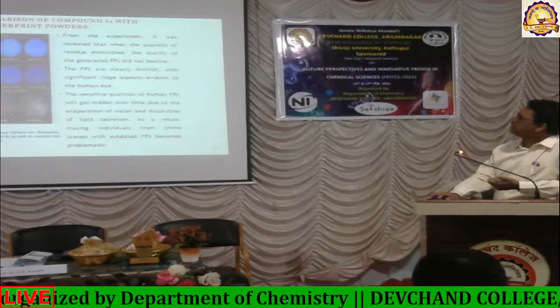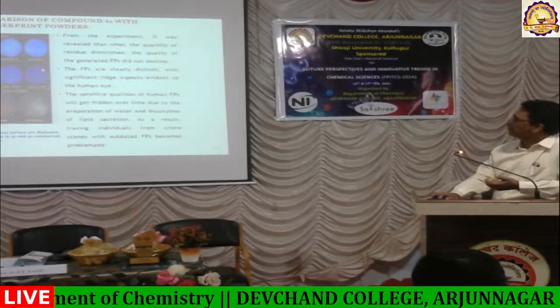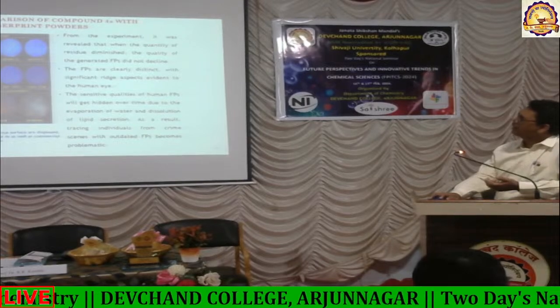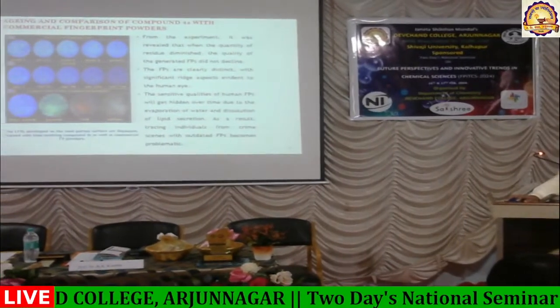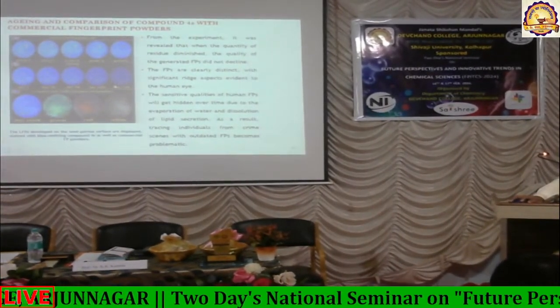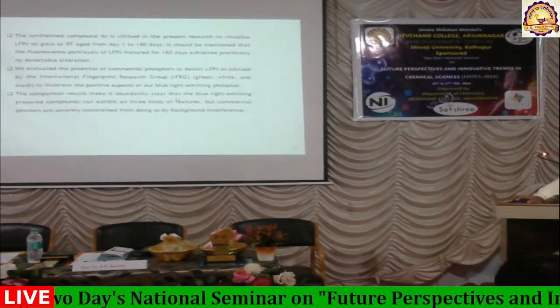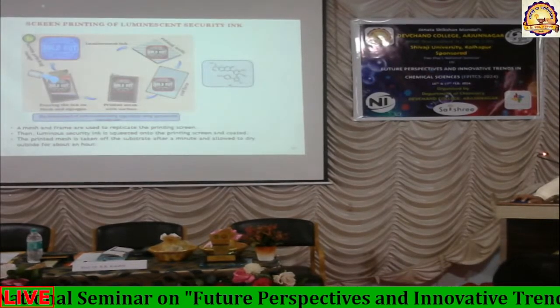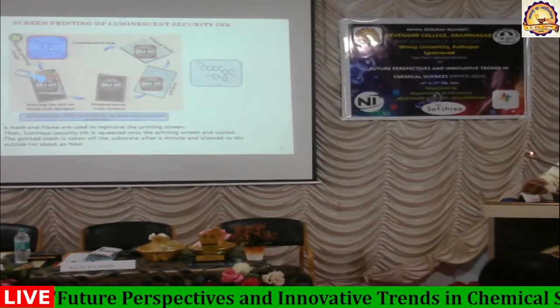So this is about aging. This is about the lifetime of this, almost like 270 days. The impression that we have taken will remain and nothing will happen with this. So this is screen printing extending to the same work.